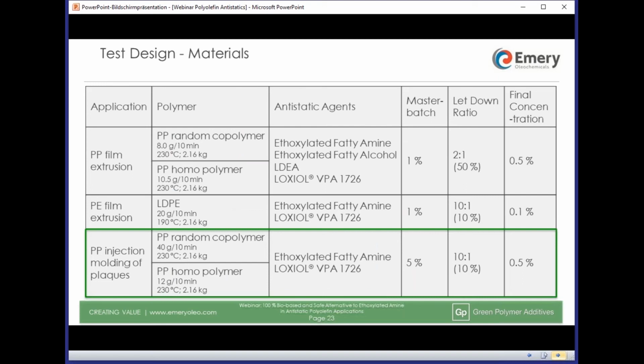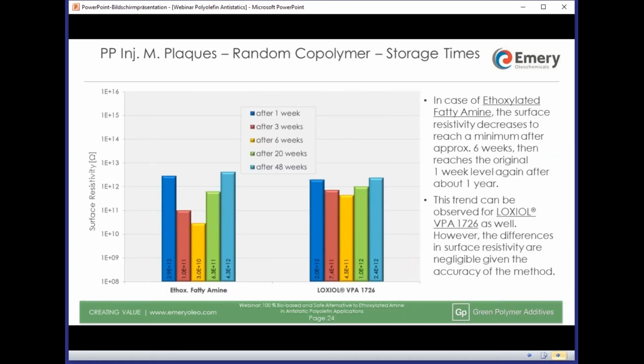Last application is PP injection molding, plaques in this case. We tested 2 different PP grades again, random copolymer and homopolymer, but different ones than for film extrusion. We have 2 result slides, antistatic performance depending on time for both polymer grades, and we waived testing the influence of humidity this time for capacity reasons. Here are the results in random copolymer PP. No big differences, and same conclusion as before. Ethoxylated fatty amine, lower minimum resistivity, LOXIOL VPA 1726, more stable performance.